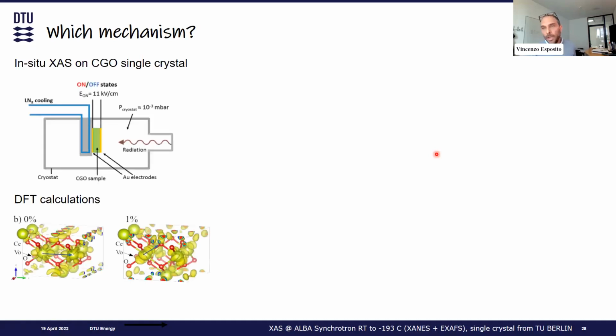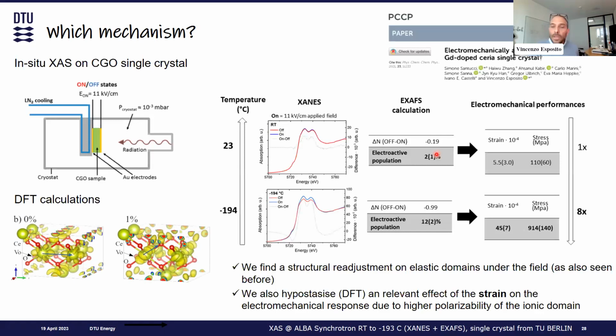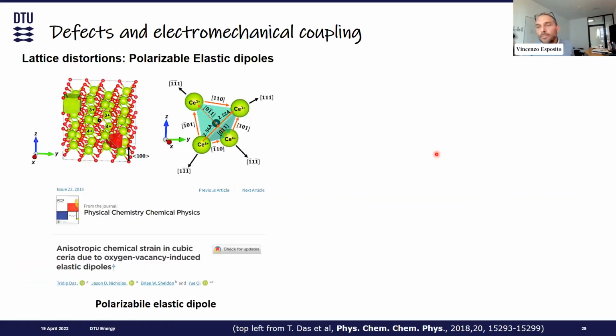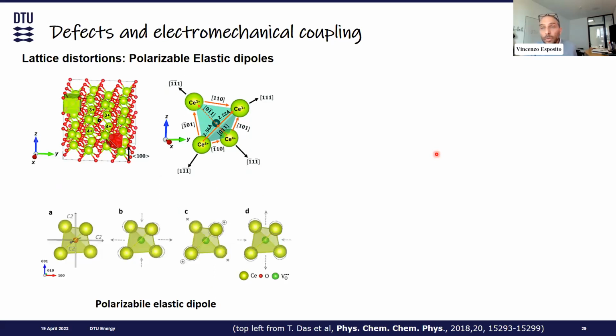But the question remains: what is the mechanism here? The mechanism is complicated, and we have been trying to disclose it using single crystals, DFT calculations, and X-ray absorption at various synchrotrons around Europe. Everything seems to be related to the fact that we have a local distortion around the oxygen vacancy in the structure. And this thankfully goes along with some models that already exist for oxygen-defective fluorites, especially CGO and cerium oxide, where around the oxygen vacancy we can create elastic dipoles.